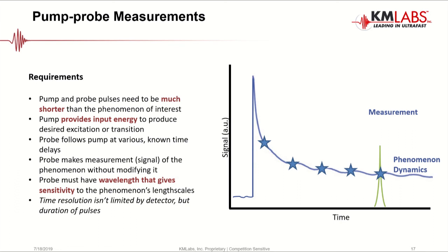The probe follows at different known time delays and makes some measurement of that phenomenon, ideally without modifying or actually impacting it, so it's a purely passive measurement. And that probe needs to have sensitivity to whatever dynamic phenomenon it is that we're trying to address, right? So there's different types of probe measurements that we can make depending on the experiment. And again, we'll see some of them. And the nice thing about all this is that the time resolution isn't limited by the detector, which is good because we don't have detectors that can go at the femtosecond or picosecond rate, but it's limited by the duration and the quality of the pulses. And that's also good because we can get quite short pulses of very high quality.